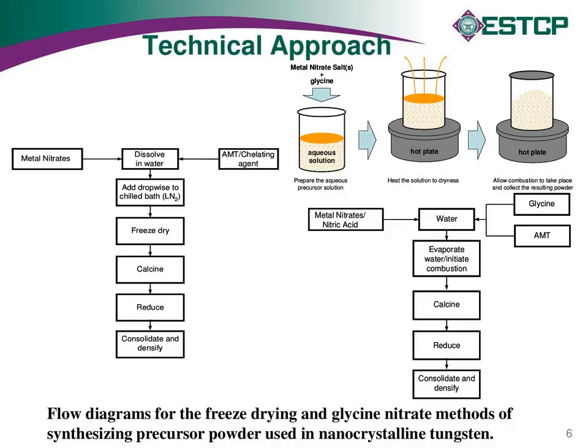Okay. Next slide. Just very quickly, there's sort of a flow chart of the two main approaches we looked at. On the left is the freeze-dry process, where you dissolve metal salts in a liquid, sublimate out the liquid, and then reduce it in a hydrogen-reducing atmosphere to produce the metal powders. The other approach we did, and was our main focus, was the glycine nitrate process, where again you dissolve the metals and the ammonium tungstate in a nitrate solution, which is heated until it dries out and then combust it, again reducing it to the metal powders in the end.